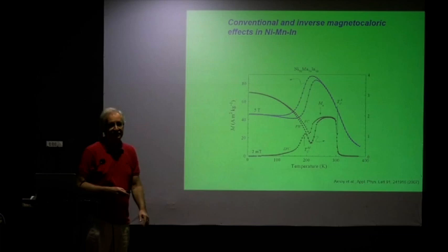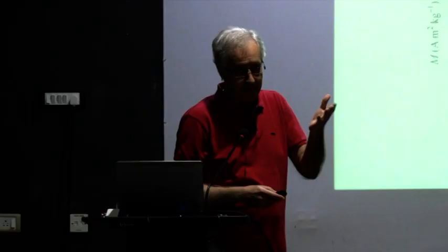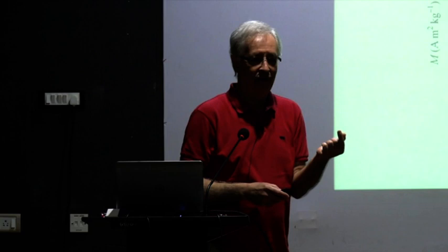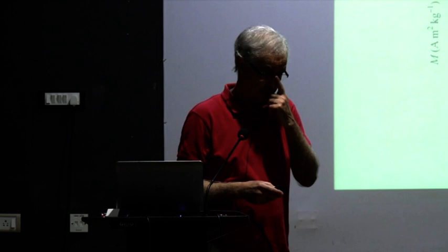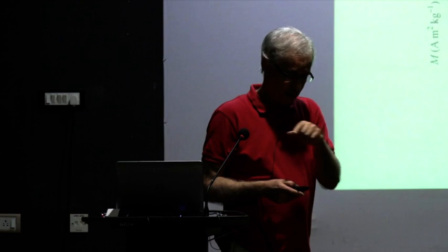Even in gadolinium, you have a single structure. We think we have a single structure. Not actually, but when you cool from the paramagnetic state to the ferromagnetic state, assuming it's a full second-order transition, there is not much change in the electronic structure, the electronic properties. So in a second-order transition, you can basically use those equations as well.